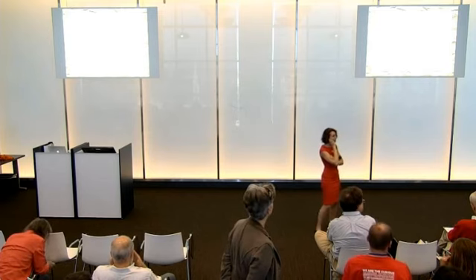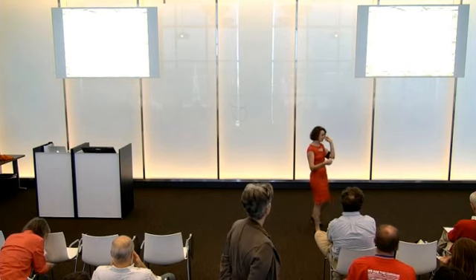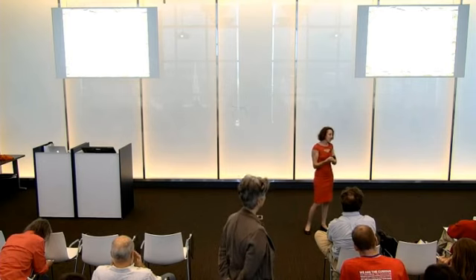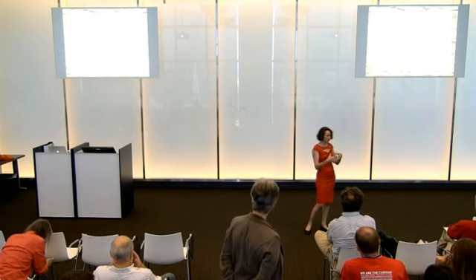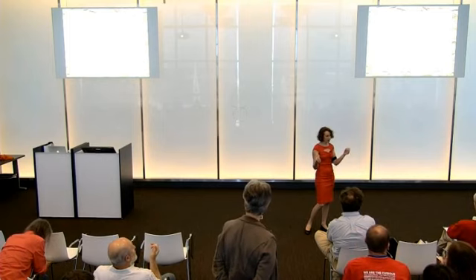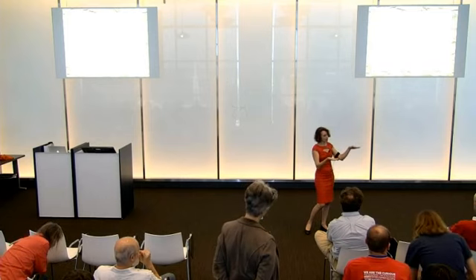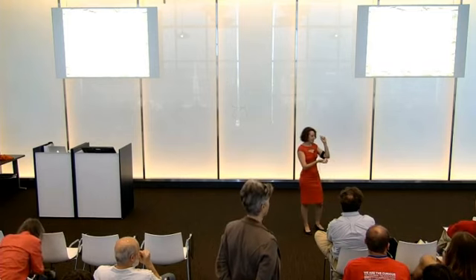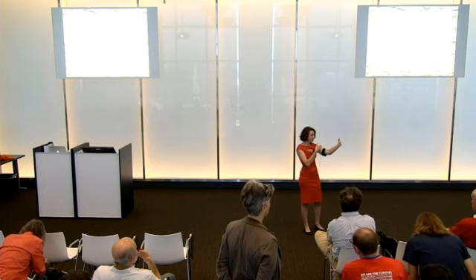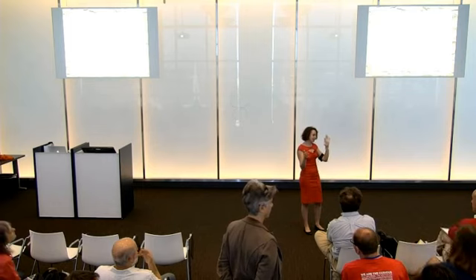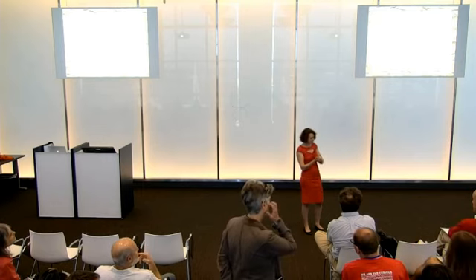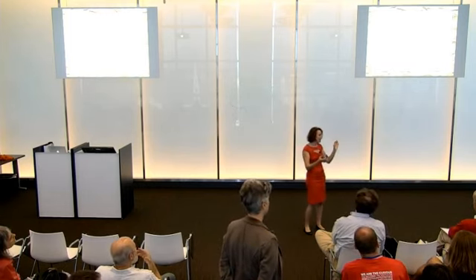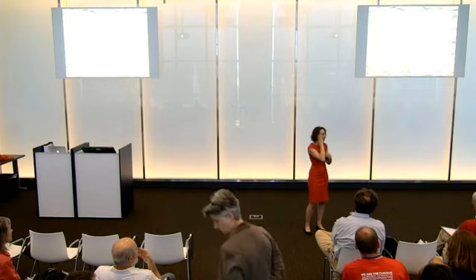Oh, yes. So we explored the size a bit, and the optimal size seems to be 7 for our system, which is why we chose to work with that. But I think there's a way to still have shapeability even if you have larger and larger systems, but it depends on the height of the system. So the ratio between the average height and the size of the system matters. If you want larger systems, you need a bigger height to obtain the same curvature of the global shape. And you can do that by prescribing random height, for example, or height that is dispersed throughout the lattice. And up and down, I don't know.